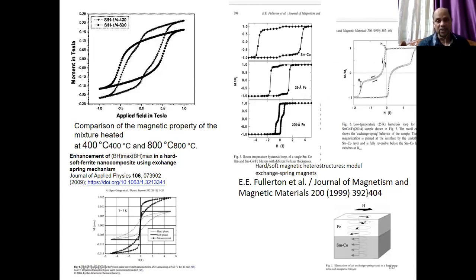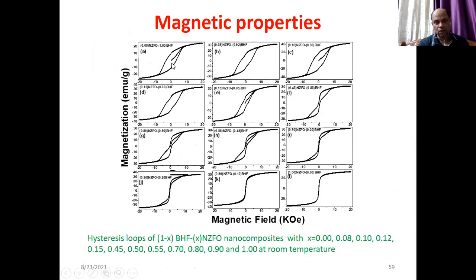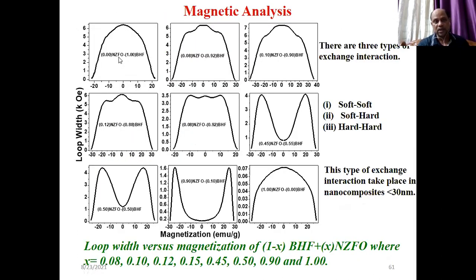Loop width versus magnetization, what is that? You just pick up any particular magnetization, and ask what is the loop width. You take the left side and right side and subtract, and you look at the magnetization. You will see that when it is a single material, even at the nano size, and this is a single nickel zinc ferrite, it is like a Gaussian, a very simple bell-shaped curve. But if you look at the composite, you will find that it is not the same. It shows a double peak. So depending upon the strength of the interaction, they change their shape.